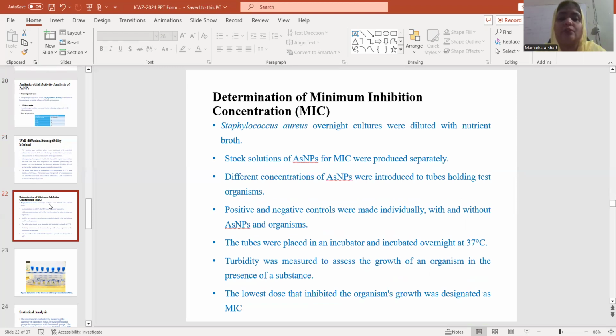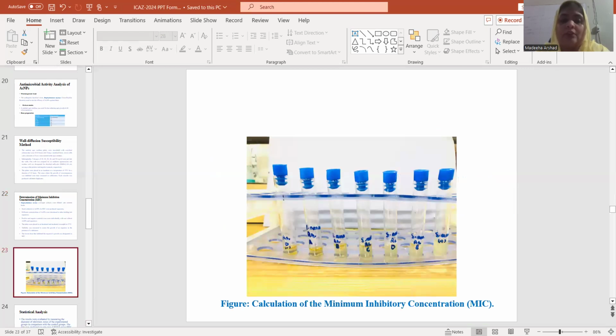Positive and negative controls were made individually with or without arsenic nanoparticles and organisms. The test tubes were placed in an incubator and incubated overnight at 37 degrees centigrade. Turbidity was measured to assess the growth of an organism in the presence of a substance, and the lowest dose that inhibited the organism's growth was designated as MIC. Calculation of minimum inhibitory concentration.